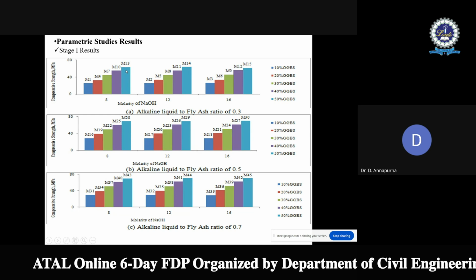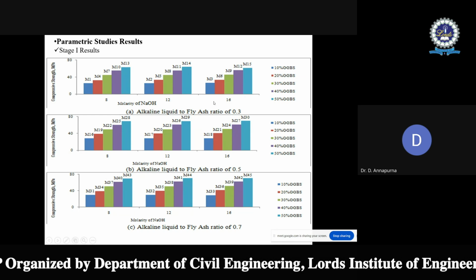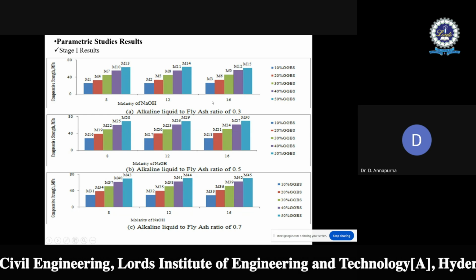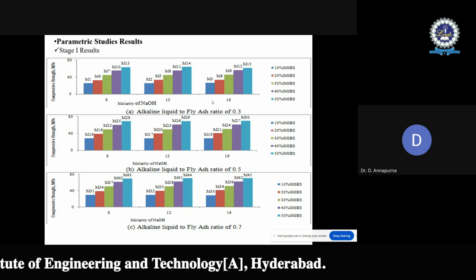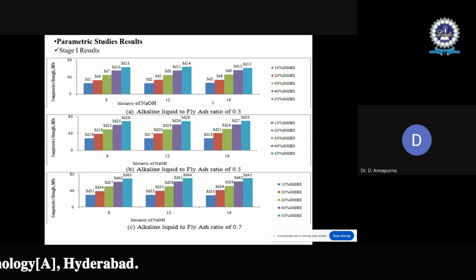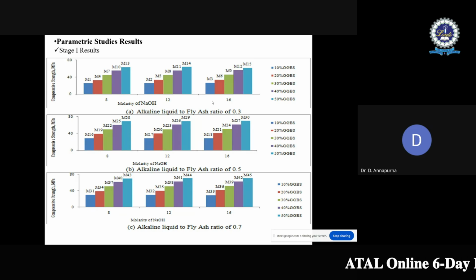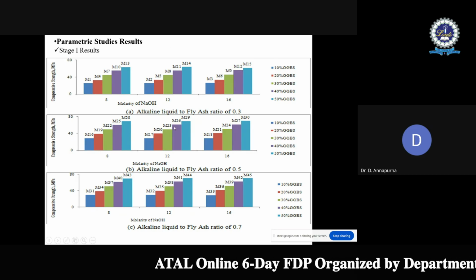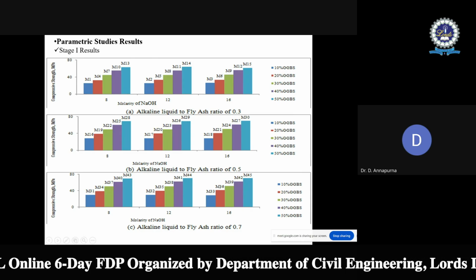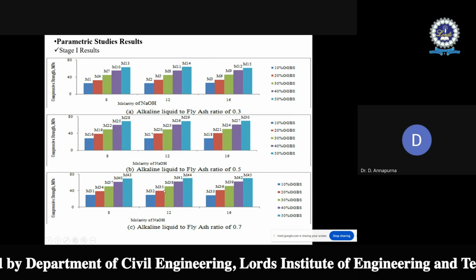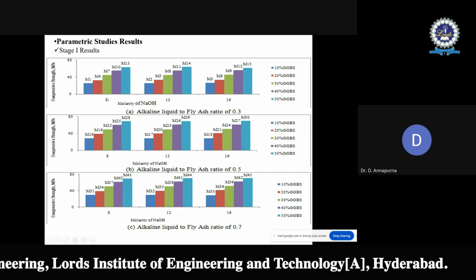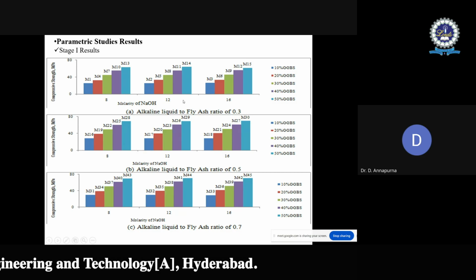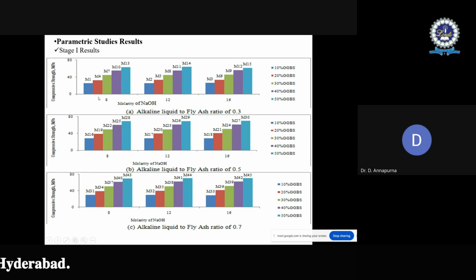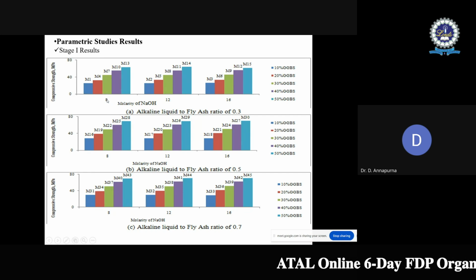So first, if you check with respect to the molarity, as the molarity increases, compressive strength increases. But in combination with GGBS, the molarity improvement shows only a little improvement in the compressive strength, that too only 4 to 6%. Almost similar results are observed in all the cases. Keeping in view the cost and toxicity of sodium hydroxide, for the next stage of work, the molarity of NaOH is maintained constant at 8.